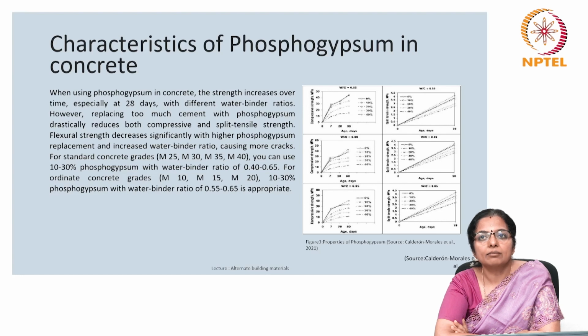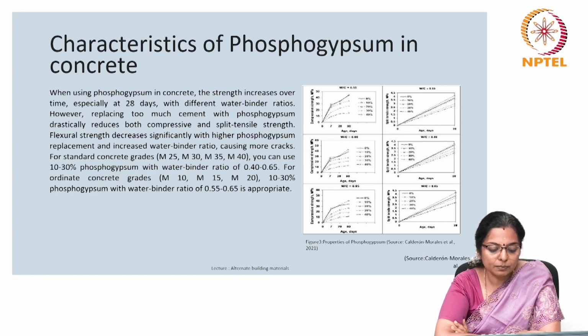For certain types of concretes, when using phosphogypsum in concrete, this strength increases somewhere around 28 days. But it should have a different water binder ratio. Now, flexural strength decreases significantly when higher phosphogypsum replacement and increased water binder ratio is done, causing more cracks. For higher grades like M25, M30, M35, M40, and so on, you can use 10 to 30% phosphogypsum with water binder ratio of 0.4 to 0.65. For ordinary concrete grades like M10, M15, M20, 10 to 30% phosphogypsum with water binder ratio of 0.55 to 0.65 is appropriate.